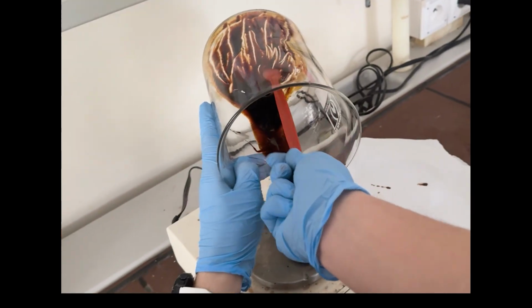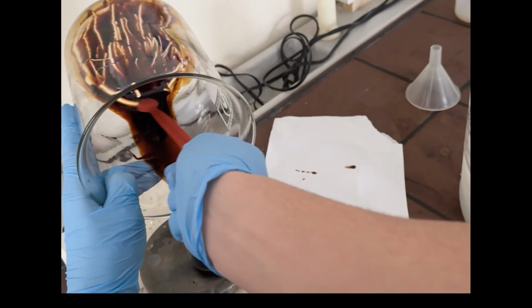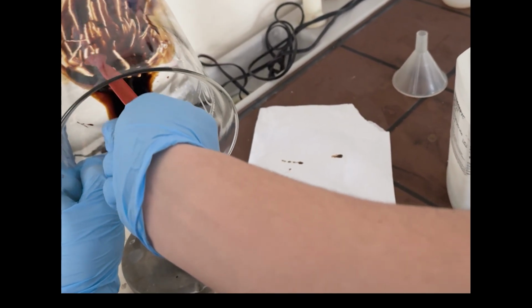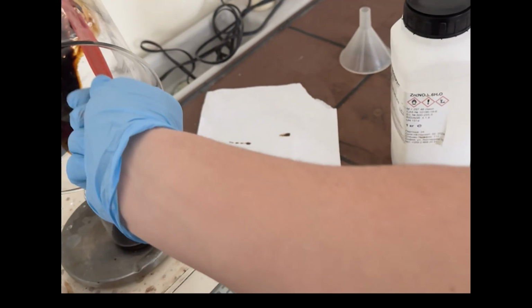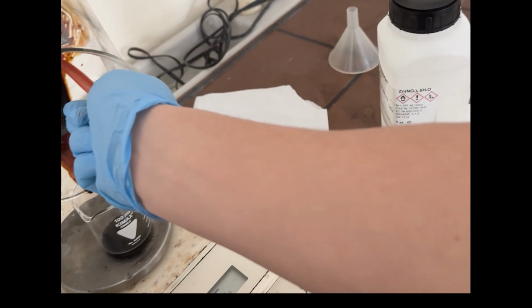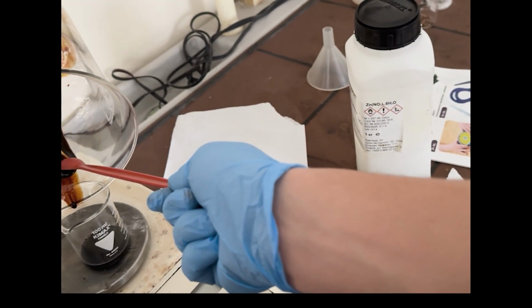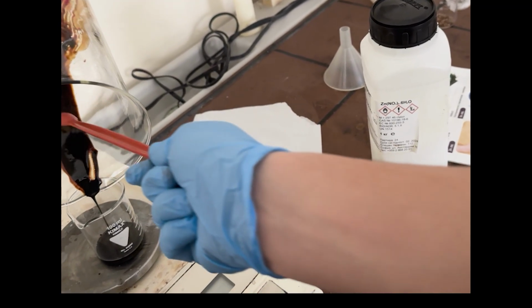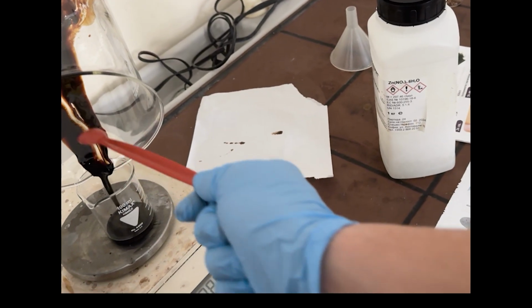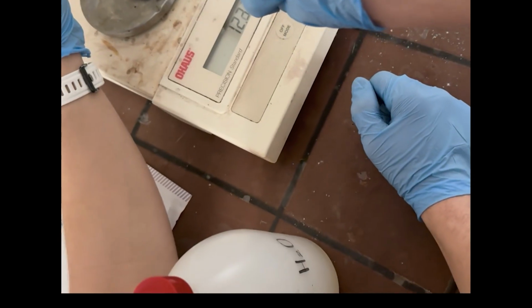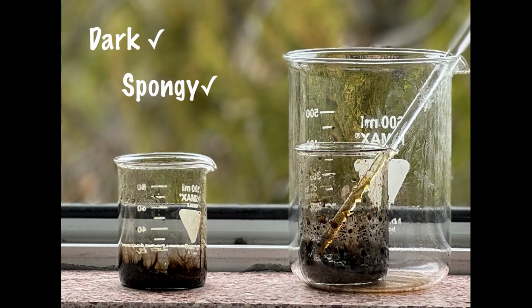In practice, things absolutely didn't go that smoothly. The imidazole contained a significant amount of byproducts, which likely interfered with the coordination and prevented proper crystal formation. Instead of well-defined crystals, the reaction produced a dark, charred, sponge-like solid, which was very hard.